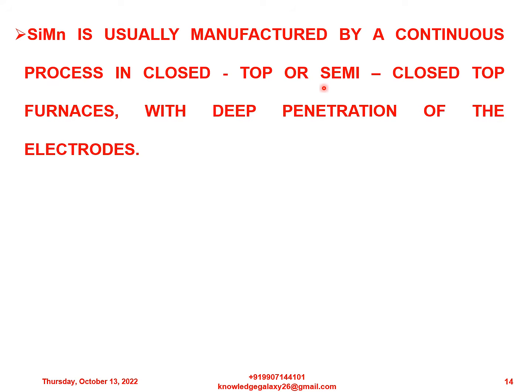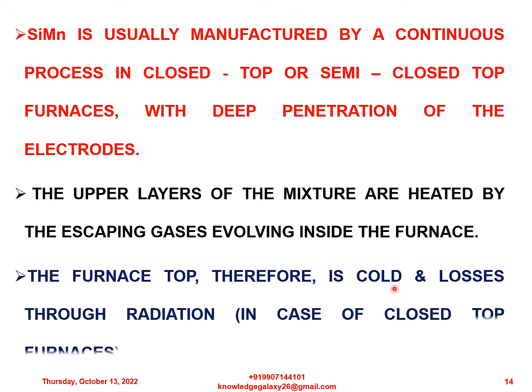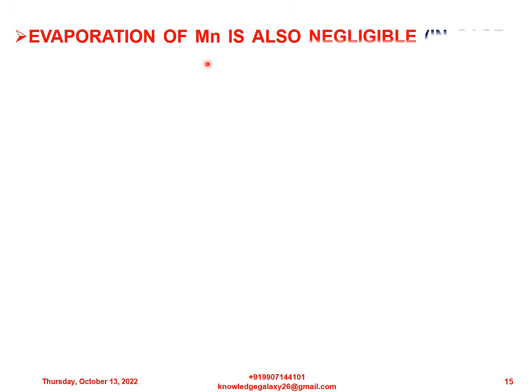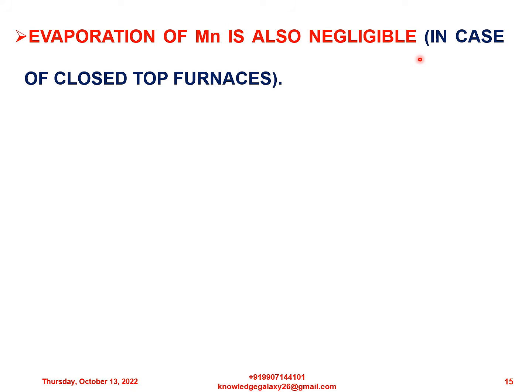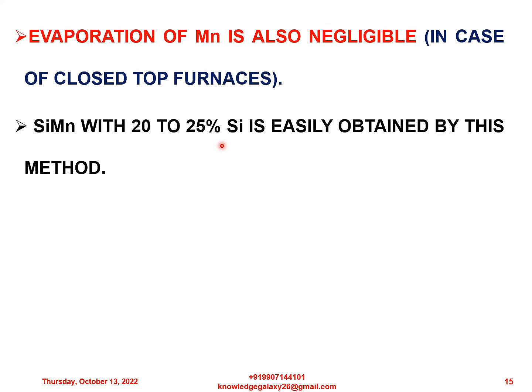Silicomanganese is usually manufactured by a continuous process in closed top or semi-closed top furnaces with deep penetration of the electrodes. The upper layers of the mixture are heated by the escaping gases evolving inside the furnace. The furnace top, therefore, is cooled and losses through radiation in case of closed top furnaces are negligible. Evaporation of manganese is also negligible in case of closed top furnaces. Silicomanganese with 20 to 25% silicon is easily obtained by this method.